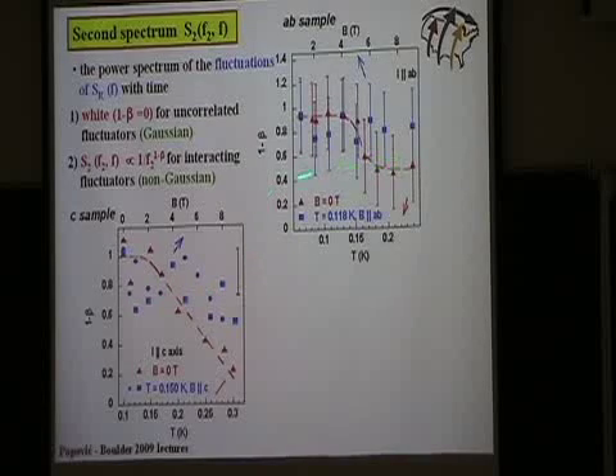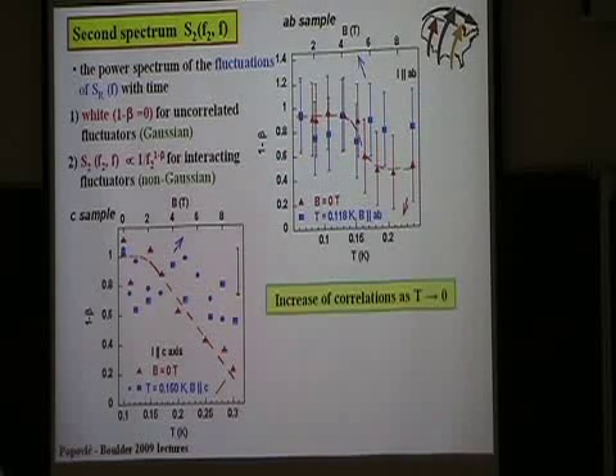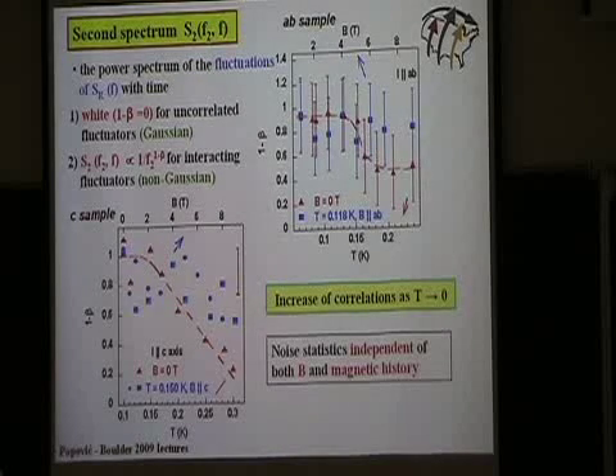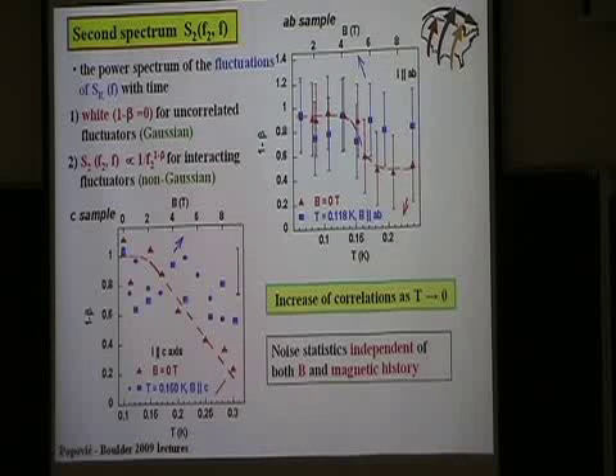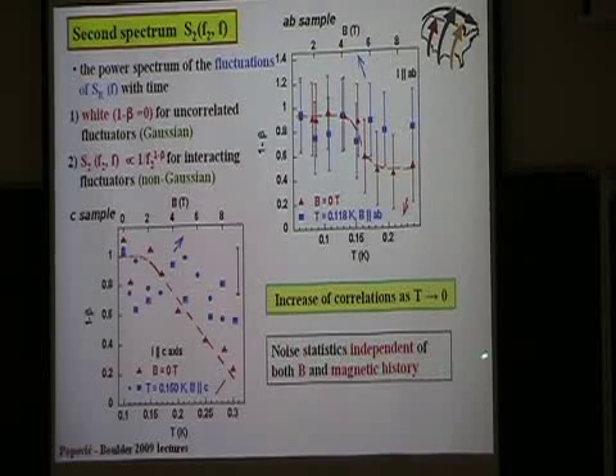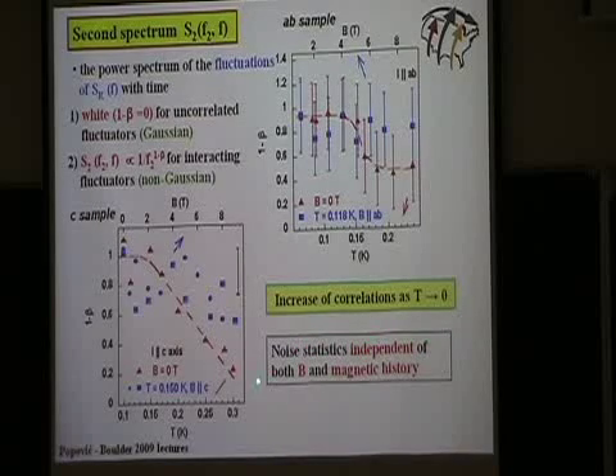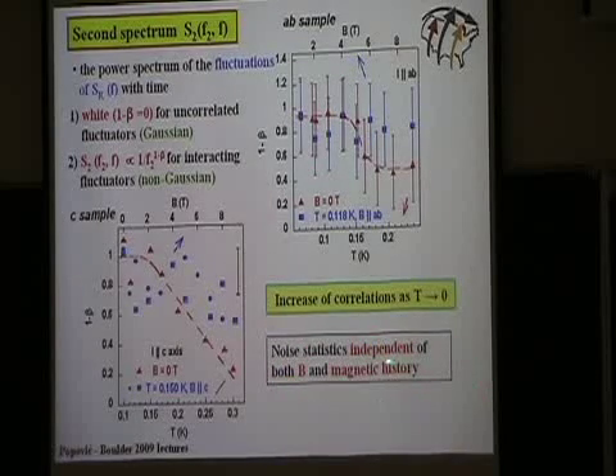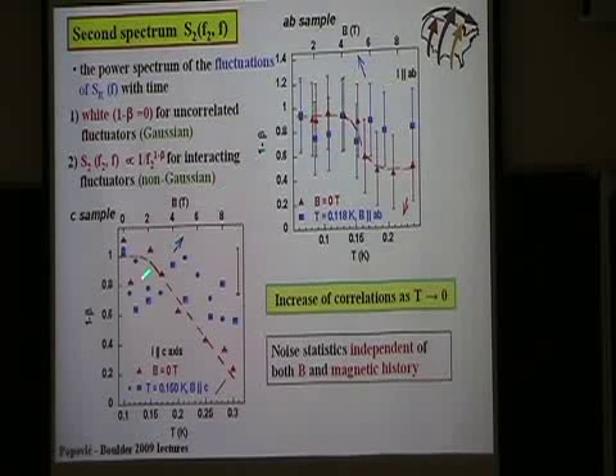And again, the magnetic field does not have any effect on 1 minus beta. So we see increase of correlations, and also the magnitude of the noise does not here seem to depend either on temperature or the field. So we established that the noise statistics is independent of the magnetic field, and we also established that it's independent of the magnetic history. For example, these data were taken after zero field cooling.